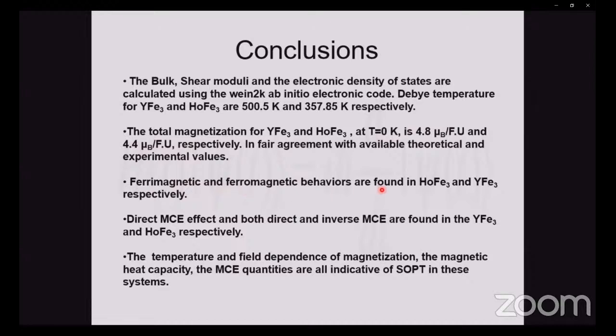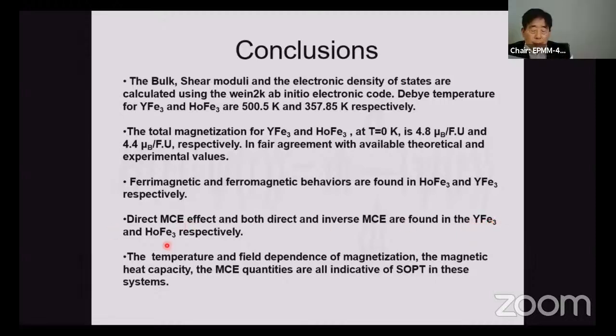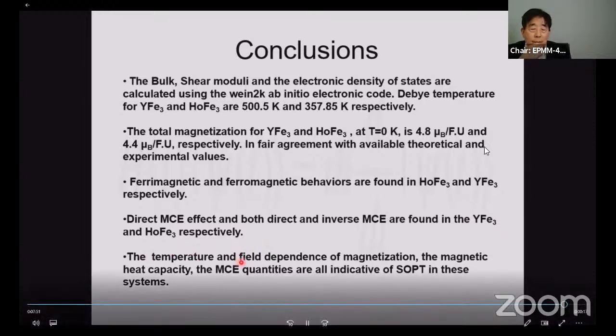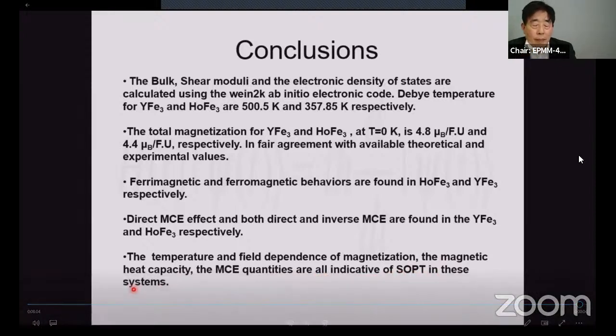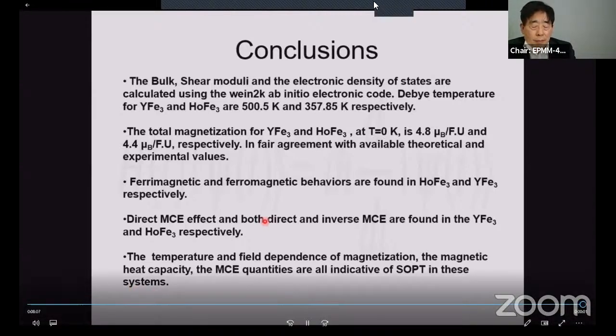Ferrimagnetic and ferromagnetic behaviors are found in HoFe3 and YFe3 respectively. Direct magnetocaloric effect, and both direct and inverse magnetocaloric effect, are found in YFe3 and HoFe3 respectively. Finally, the temperature and field dependence of magnetization, the magnetic heat capacity, and the magnetocaloric effect quantities are all indicative of second order phase transition in these systems. Thank you for your attention.